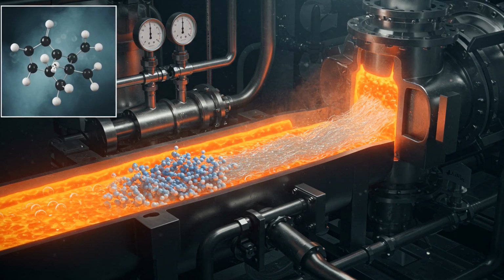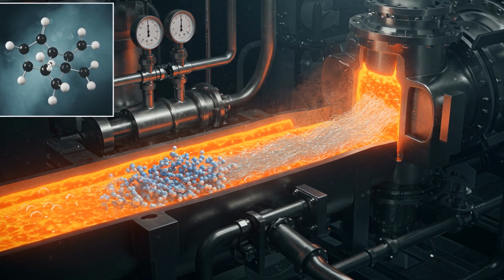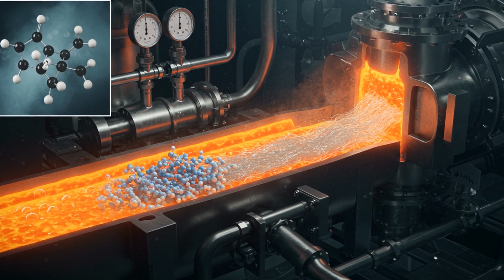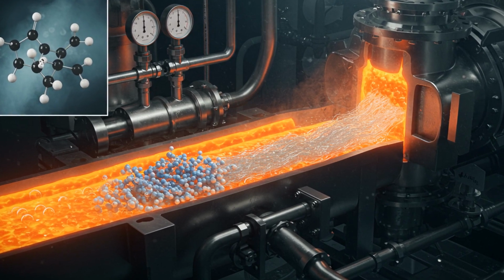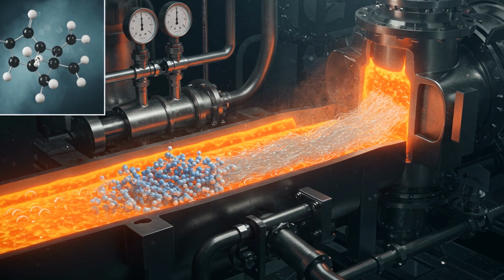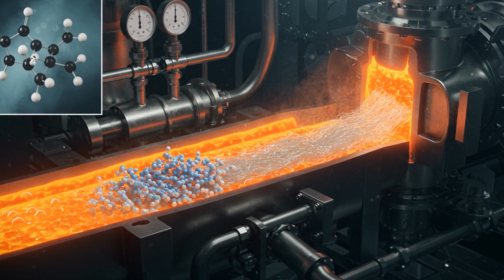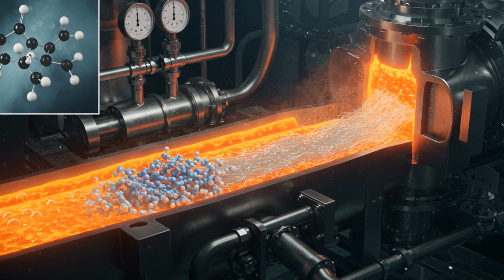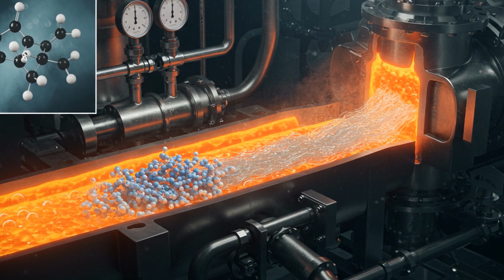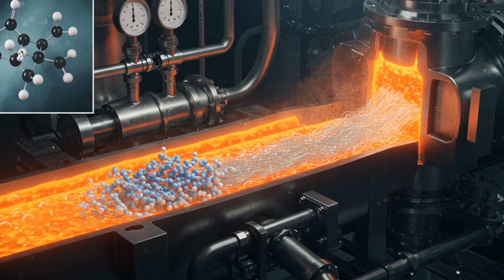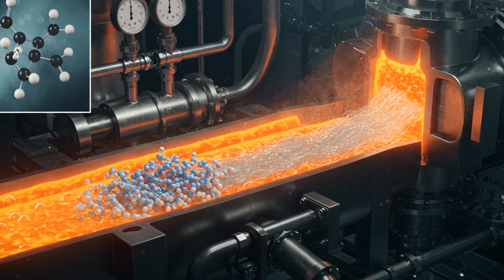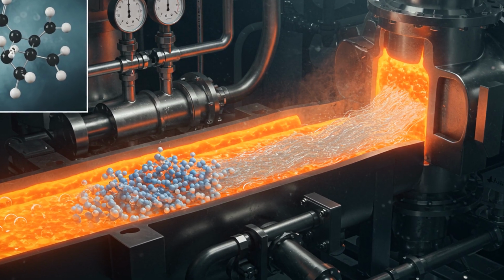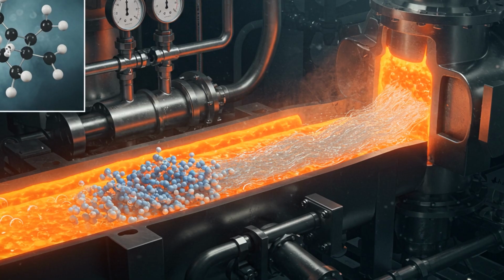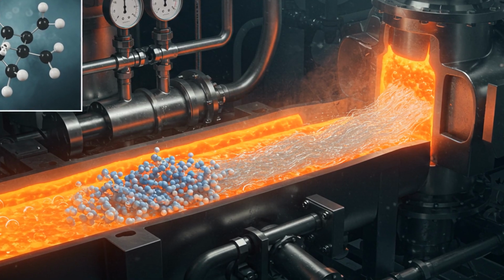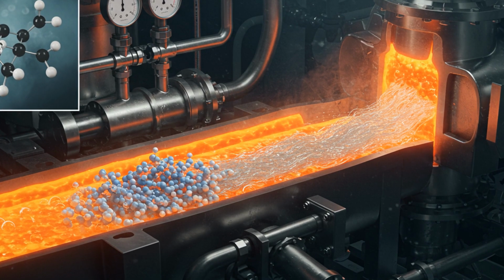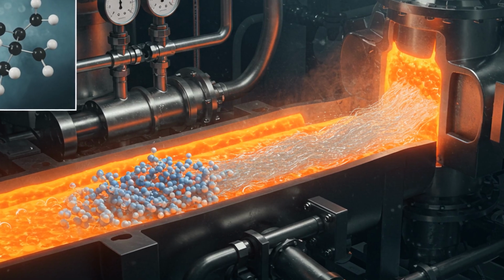Polymerization is where chemistry becomes macroscopic material. For nylon 6,6, manufacturers first make a nylon salt by neutralizing adipic acid with hexamethylene-diamine in water. The salt is dried, then heated under vacuum in a reactor to drive the condensation reaction. Water is expelled as each amide bond forms, and operators control temperature to keep it flowing yet stable. Typical melt polymerization temperatures are around 260 to 280 degrees Celsius under reduced pressure to pull off water and push the reaction toward longer chains.